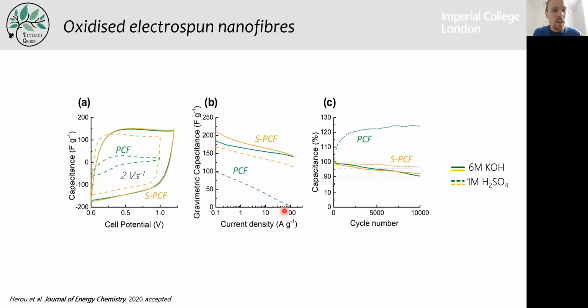And so we've been wondering why is that? Why could such a small difference in oxygen groups allow such a big difference in capacitance retention and energy density? So we cycled the device 10,000 times, and we observed that for the non-stabilized fibers, the capacitance slowly increases until 125%, whereas the stabilized sample is fairly stable. And that basically tells us that this sample is not very well wetted, so there is a low accessibility of the electrolyte ions to the porous structures. And this is why the more we cycle the device, the more the electrolyte is able to penetrate the porosity.